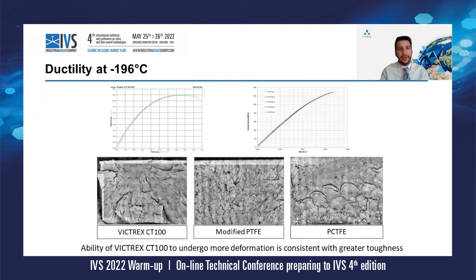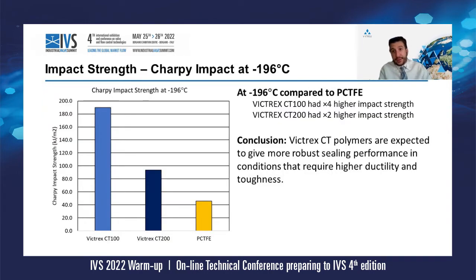Having a material ductile, and ductility is never a simple thing when the temperatures are going so much below zero. So as expected, of course, both the CT100 and CT200 offer a higher strength, being at the same time more ductile. So a combination of properties which become even more important if you have a relatively high pressure, let's say. So also the impact strength is quite important, and you can see that VICTREX CT100 has a 4 times higher impact strength, while CT200 has a 2 times impact strength. So it's a more robust sealing, but at the same time more ductile. Both of the materials, of course, CT100 we are seeing it's even better than CT200.